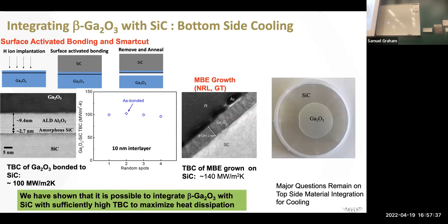And so beta gallium oxide is fairly resistive. That's why you have to have it fairly thin. And so by using TDTR, it goes through that interface, it goes into the silicon carbide underneath, and we're basically using different frequencies and multiple measurements to try to back out the thermal conductivity of this layer as well as the thermal boundary conductance, because we know the thermal conductivity of the silicon carbide.